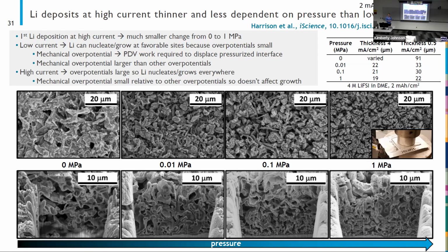At high current, we have lots of overpotential related to kinetics and related to transport. And so now we have a totally different story. And since those other overpotentials are so large, the mechanical overpotential doesn't play a role because it can't compete with those. There are other bigger barriers in the system. So we don't see a change in the morphology because that's not what's controlling it at that point.